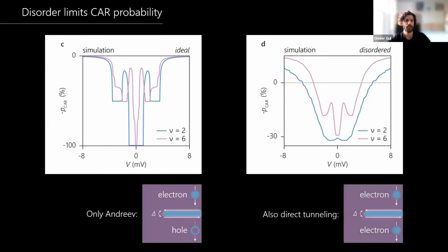This disorder switches on direct tunneling, which is not possible in the ideal case because it corresponds to left mover tunneling to the right mover along the superconductor. This process does not conserve momentum and is only allowed when disorder is present, which is the experimentally realistic scenario. Decoherence processes, such as vortices in the superconductor, further decrease the probability. Another noteworthy feature here is that the positive signal at large energies is due to direct tunneling. The CAR signal never changes sign in the ideal case.